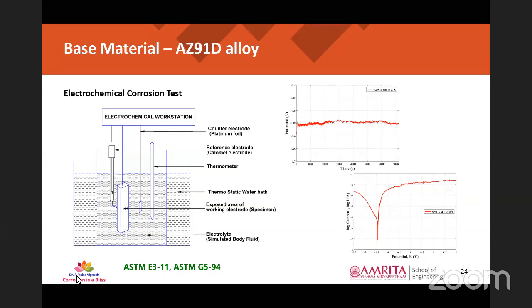So the characteristics of this anodic and cathodic part will be detailed when we discuss this composite. Okay, so from this also we come to a conclusion that the corrosion rate of the specimens with this electrochemical corrosion test is around 4.49 mm per year, which is very close to the immersion corrosion results too. So this is the basic results that is from base material, that is AZ91D.